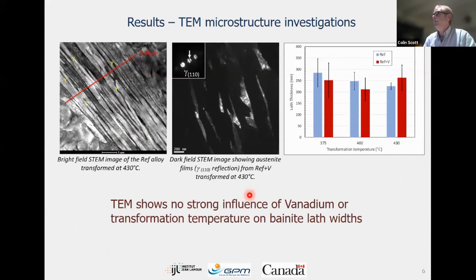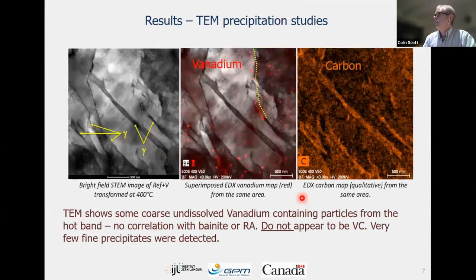If you go to the TEM, which is what you do next, you can see this nice lower bainite structure again. We measured the lath thickness. So this was done in the TEM for all the temperatures and for the two alloys. We couldn't see any effect. There's no obvious influence of vanadium on the bainite lath width, either in the TEM or in the SEM. So that's quite clear. Doesn't change anything there.